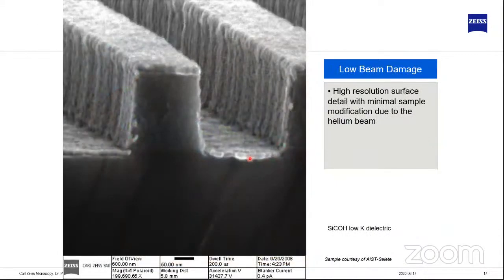This does not only work for biological samples, it works for all kinds of samples. And what is also interesting is that sometimes ion beams are actually less harmful to a sample compared to an electron beam. So, and this is an example for that. So this is a low-K dielectric coating here on a semiconductor device. What you typically want to do in these structures is you want to measure the sidewall here. We want to measure the dimension of this groove and the shape of this line here.